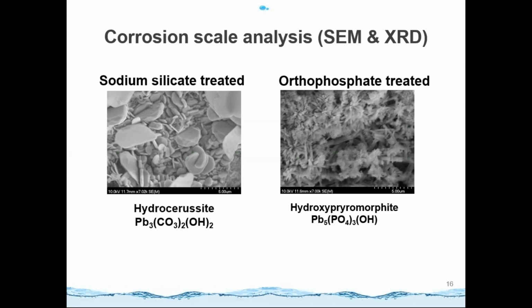We identified this corrosion scale as hydrocerussite, which is a very common lead carbonate in the distribution system. And based on the XRD data in the orthophosphate treated system, we identified the corrosion scale as hydroxylpyromorphite, which is a very common lead phosphate solid. Lead phosphate solid usually appears in the orthophosphate treated system, and it has very low solubility.